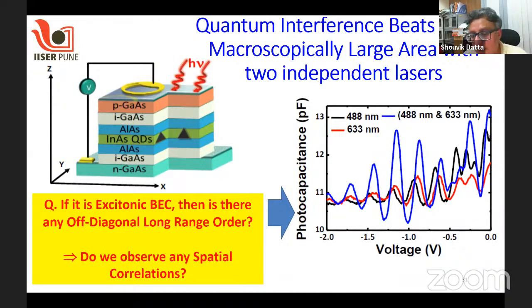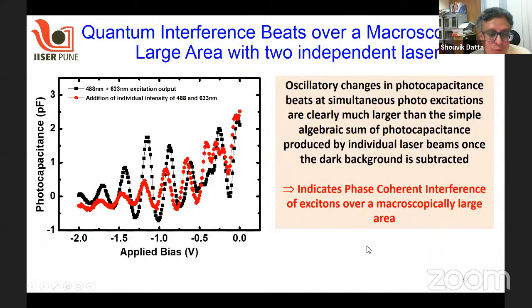So what we did is that we tried to measure oscillations with two different lasers simultaneously. As a result, what we see is very interesting: although these laser spots are macroscopic, covering nearly 200 microns of area, when you actually excite them with both lasers, the oscillatory changes in photocapacitance at simultaneous photoexcitation intensities are certainly much larger than the simple algebraic sum of photocapacitance of the individual laser beams.